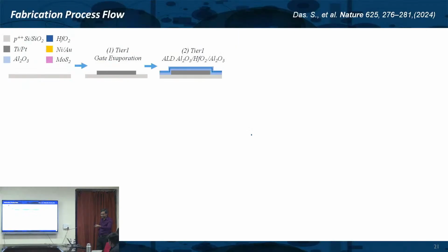So first we do this tier 1 gate. First we do the gate, then we transfer, then we do the gate oxide, which is our floating gate. Remember, this is what we want to integrate memory and logic. So we do this alumina, hafnia, alumina. Then we do an etching process, which also requires e-beam lithography to define the pattern, then go and etch it, right? So e-beam is involved with the etching.